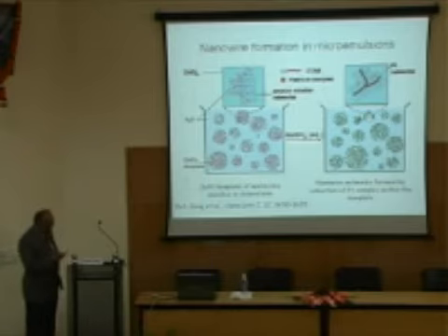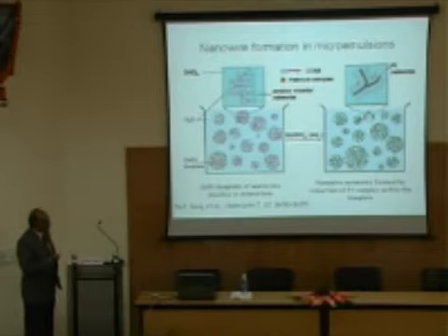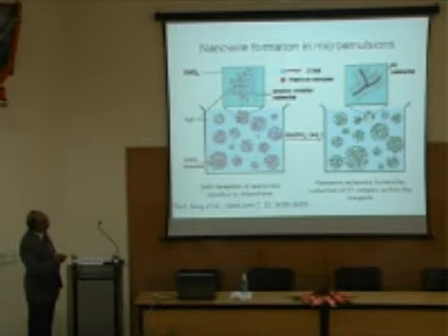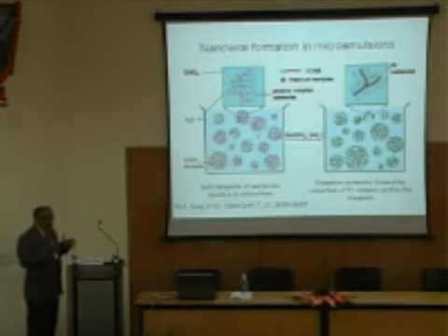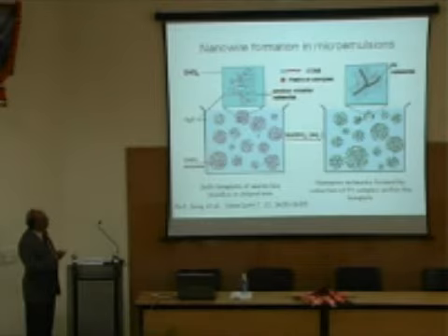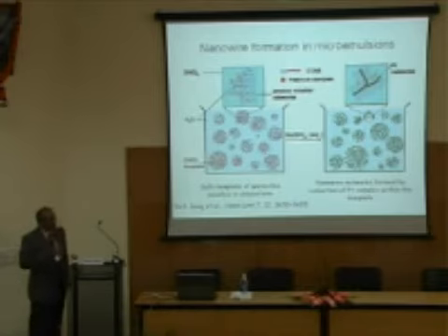So depending on the nature of the initial molecules that you take, you will get different types of structures. In this case, it's like a worm-like micelle. It is not allowing the particles to grow freely. It is channelizing them in a particular fashion. So all the platinum is growing along a particular direction, and it forms this kind of Y junctions. In today's world, these are called Y junctions. But you can get linear nanowires or many other things.